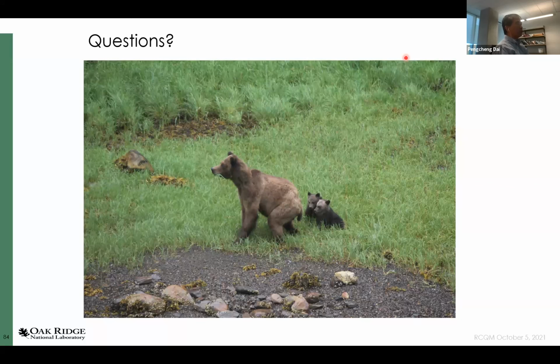But does that affect your continuum? No, that continuum that we see appears to be quasi 2-dimensional. So I would say no, at least at the level that we are able to measure it. Now, of course, in order to see it in these time of flight measurements, well, I'm going to back off on the no in a second because I'll talk about the measurements with the triple axis. But in the time of flight measurements, you have to integrate, as you know, over some non-zero momentum thickness perpendicular to the plane. So you're always doing that.